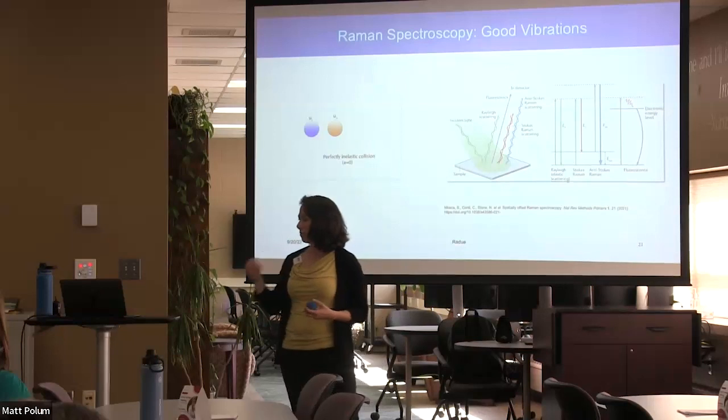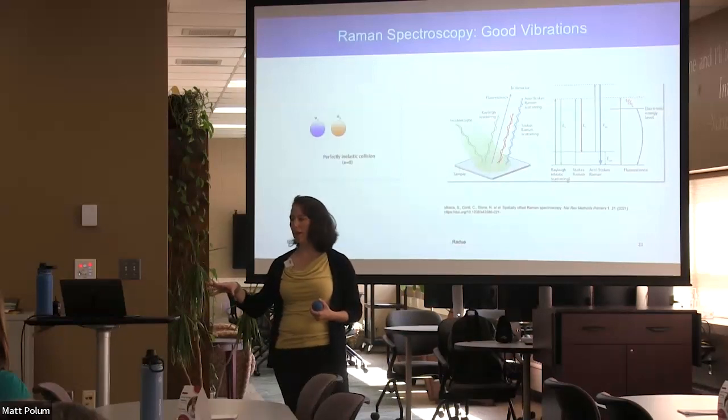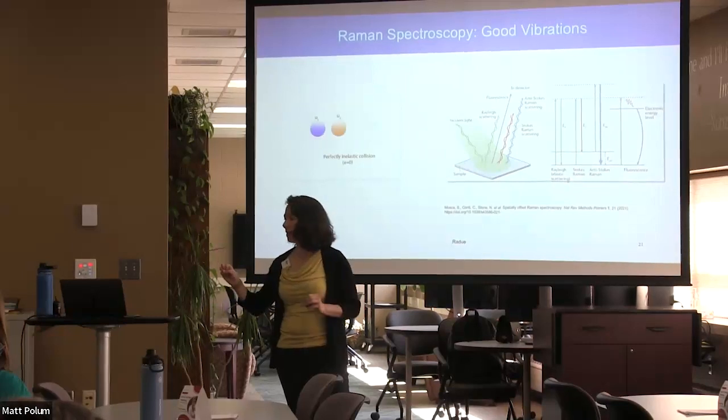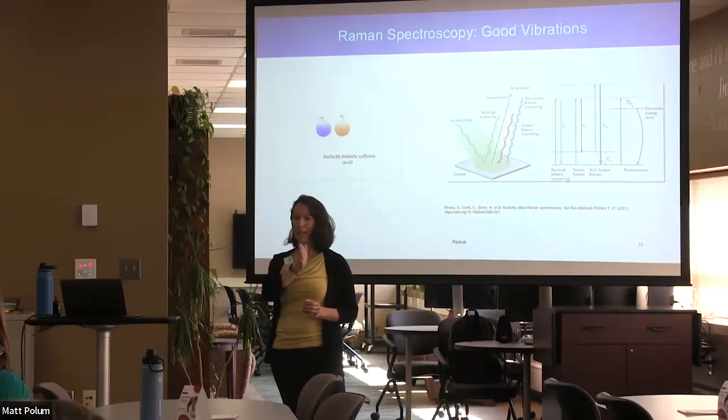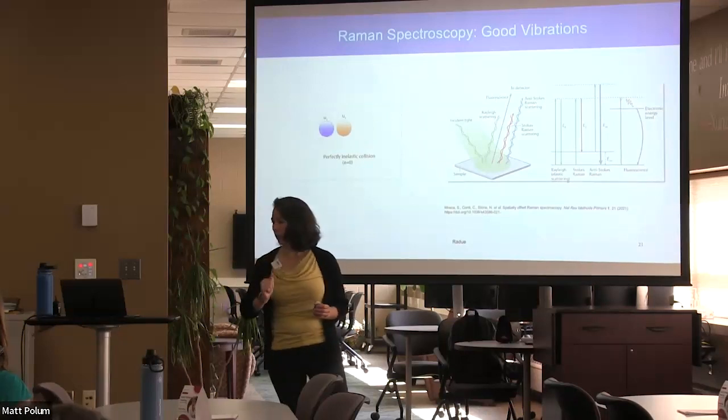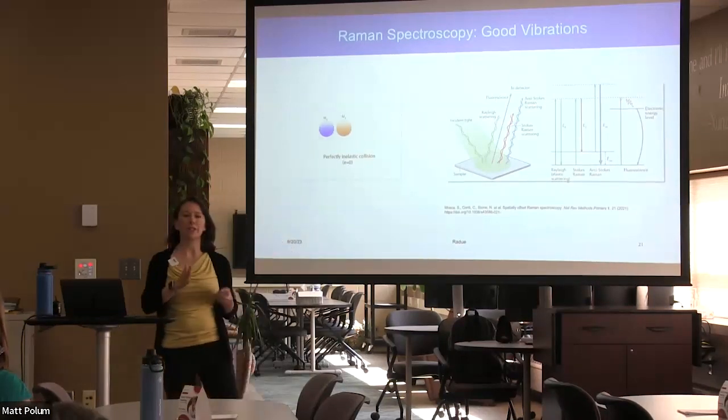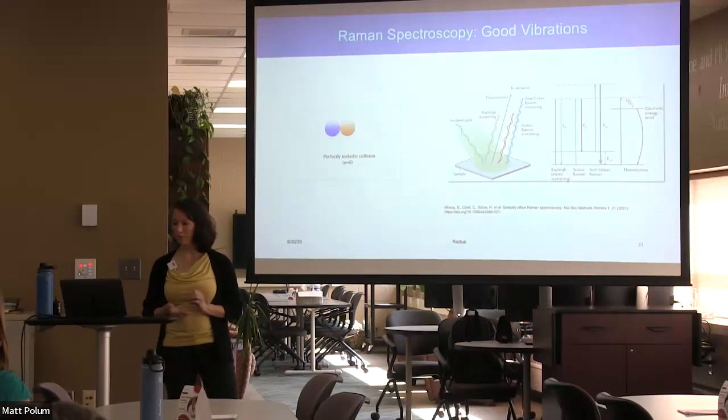So sometimes the light hits the material and it loses a little bit of energy, and that energy goes to the phonons. And sometimes it gains a little bit of energy from the phonons. So you'll see a little shift in the light, either to red or blue. And by looking at those shifts, how much it's shifted by, how powerfully it's shifted, again, we can see, okay, we got phonon mode there, we got wiggles there, we got wiggles there.